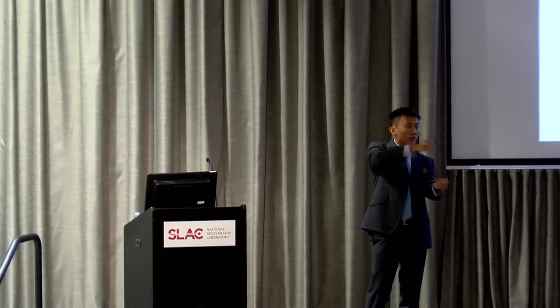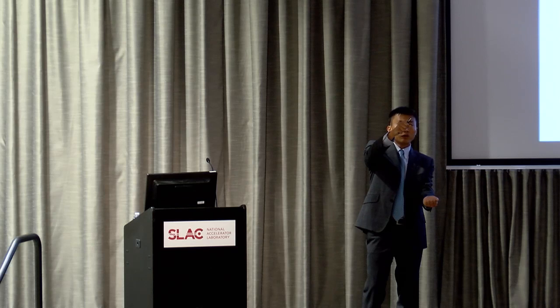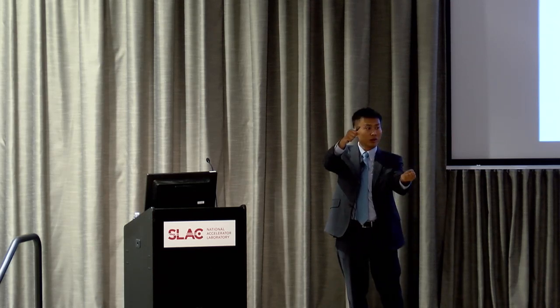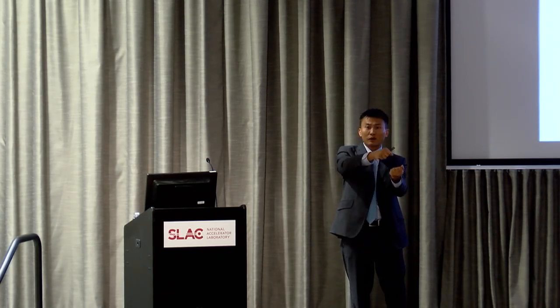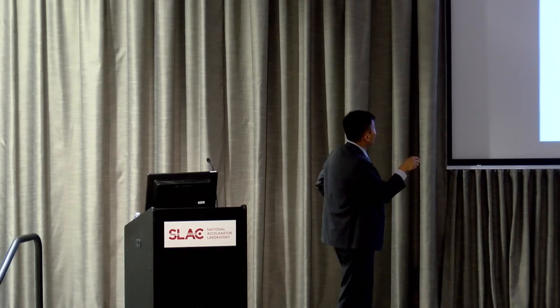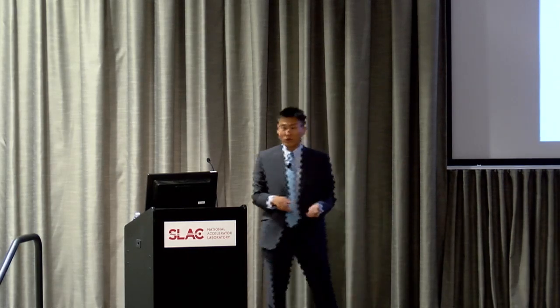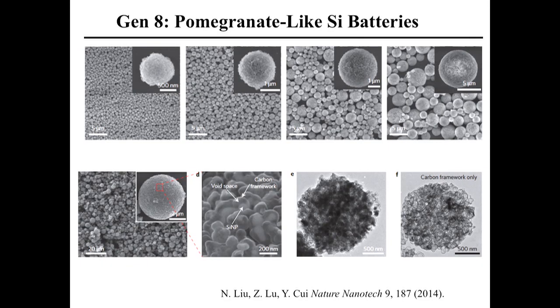If they don't pack very well, occupy too much volume, even if the individual particle can store a lot of lithium, you waste a lot of space, so that's not good. So we designed this. It's called a pomegranate-like structure. So we made this, right? So this is nanoparticles packed into about 1 micron in diameter. This probably has 50,000 nanoparticles in there. Once you get to here, there's a few hundreds of thousands of particles all packing together.